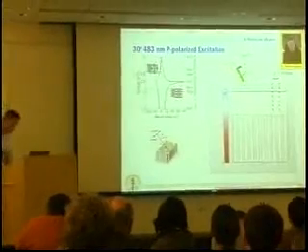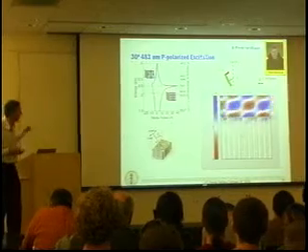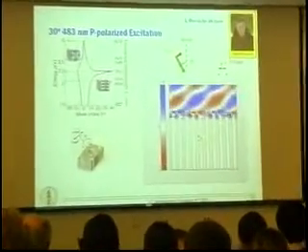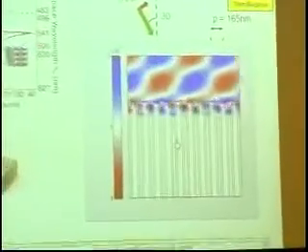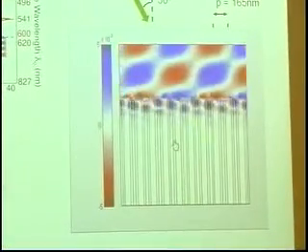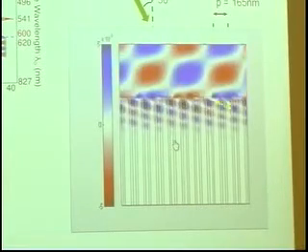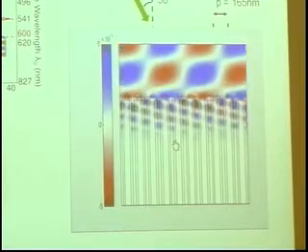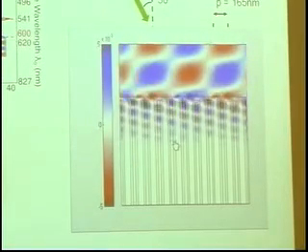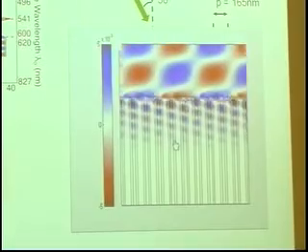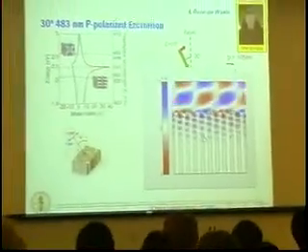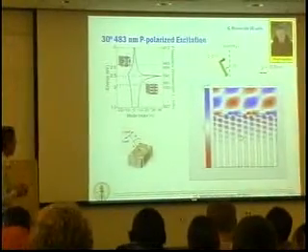So for example, this is one example of this strange material that we're working on. If we have light incident here on the material, this is light coming in at an angle and reflected. Now you can see here the phase fronts are coming in, optical power is flowing down as the amplitude penetrates into the material. But you can see the phase fronts are moving back towards the interface. And in fact, the orientation of the wave coming in is like this, and the orientation of the refracted beam is like this. So this illustrates the opportunities we have for dispersion engineering in a relatively simple material. This is just a single thin film of silver that happens to have been made in a somewhat special way.